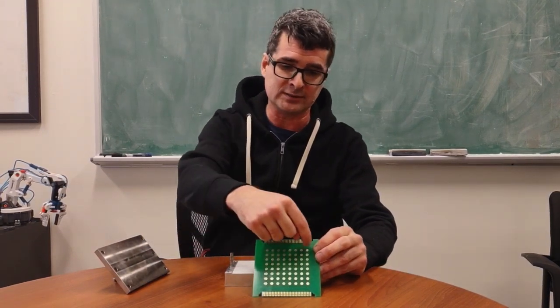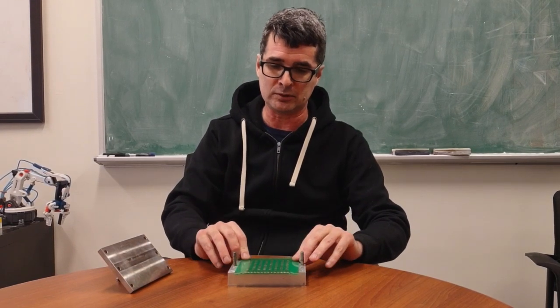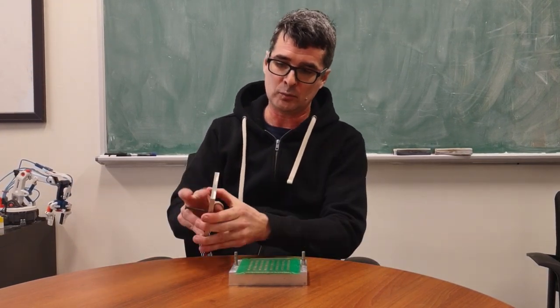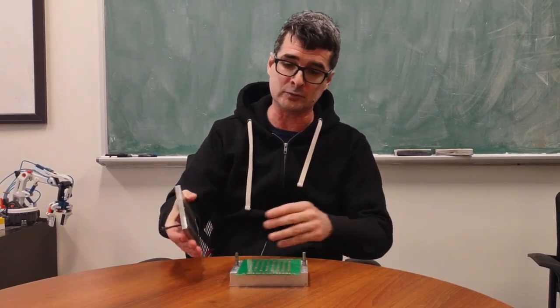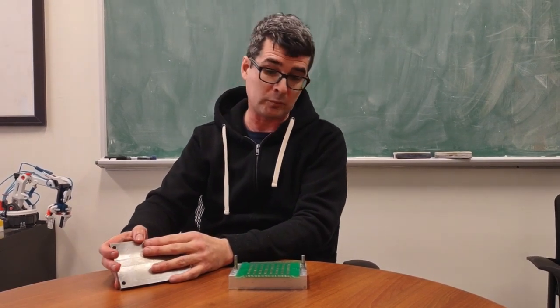And the electrochemistry, which we test in our high throughput cell. So we deposit 64 different electrodes on this printed circuit board and then assemble it into a single cell with one piece of lithium on the other side as the counter, and then cycle them doing cyclic voltammetry. So this is our usual methods in the group. And when we did this, we found some really strong performance.